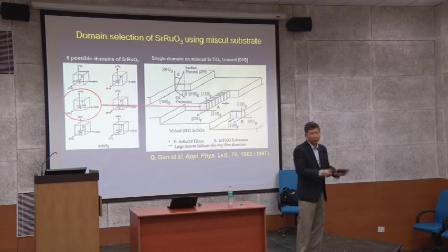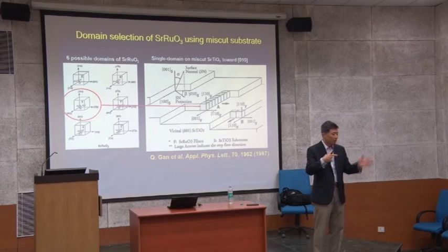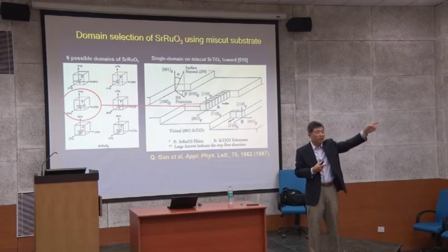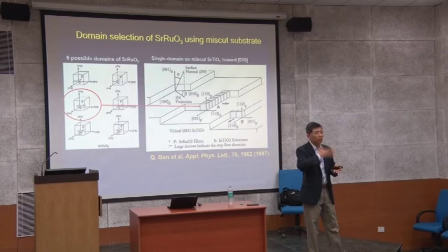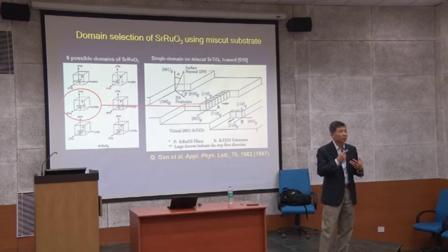So this laser beam uses the helium neon laser, okay, red laser, reflects off the surface, and I can see the spot over there. That is coming from the surface. Okay? So I know what the surface plane reflecting is. But X-ray diffraction is not from the surface. X-ray diffraction is coming from what? The crystallographic plane. Do you understand that? The crystal plane and the surface plane are not the same.